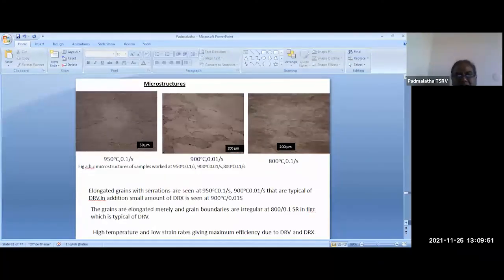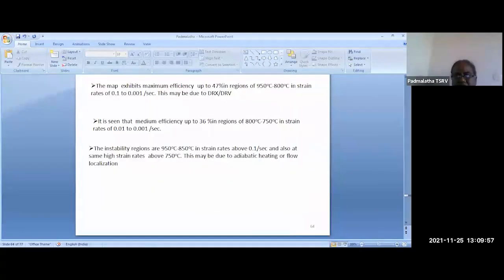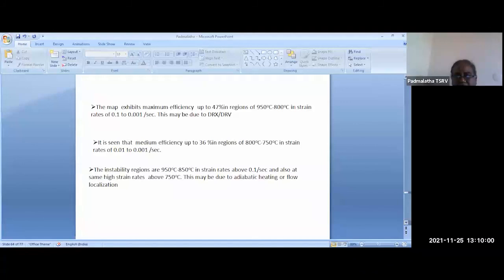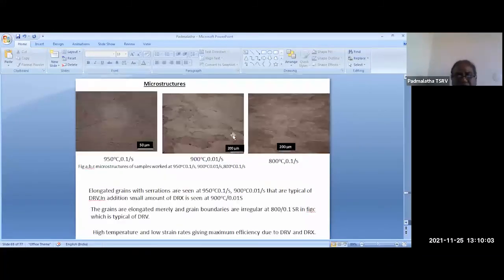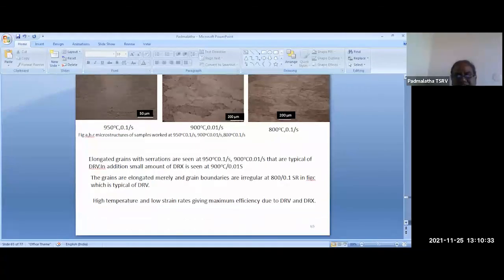by microstructural evaluation. So when we went for microstructural evaluation, usually at low strain rates, what we have seen are irregular grain boundaries, and small recrystallized grains also. See all these irregular grain boundaries and these elongated grains, these are typical of DRV. DRV means dynamic recovery. So the dynamic recovery phenomenon is happening inside the material. So you see all these serrated grain boundaries, they indicate that dynamic recovery is happening inside the material, which is good for us. So these are the safe regions.